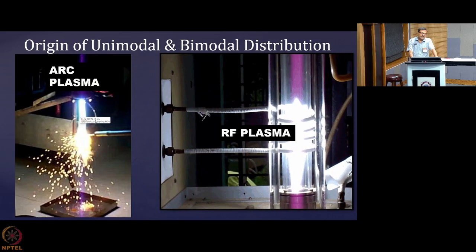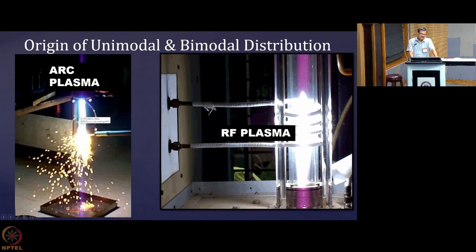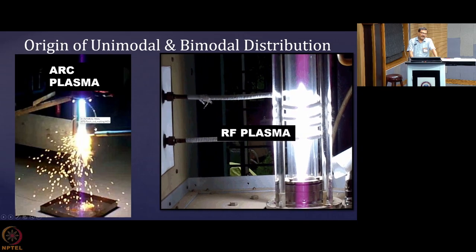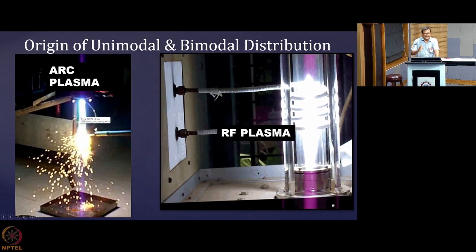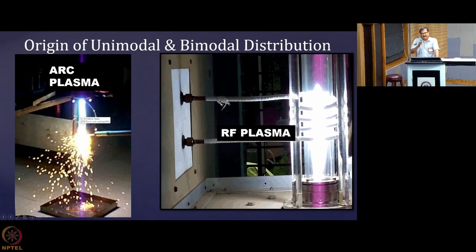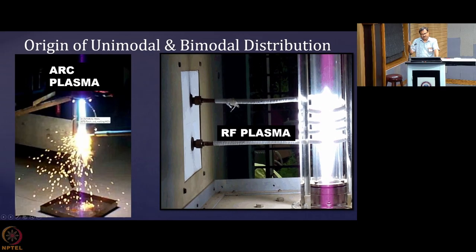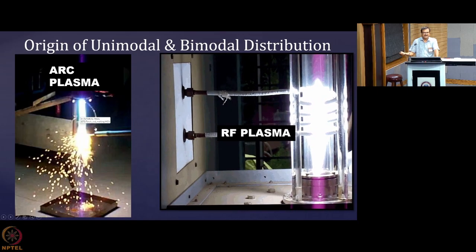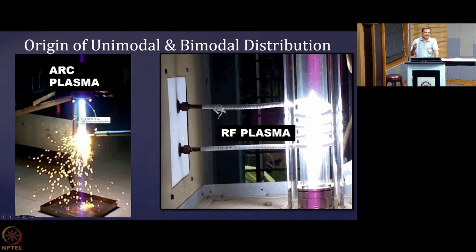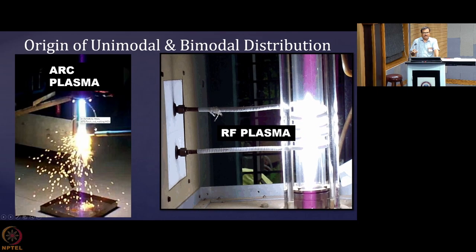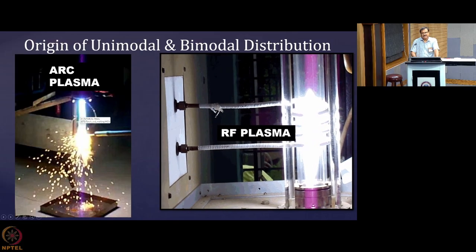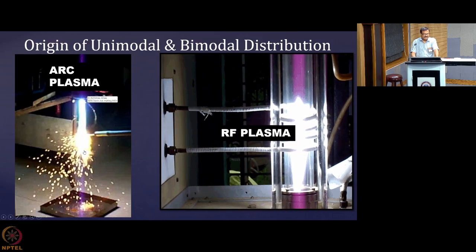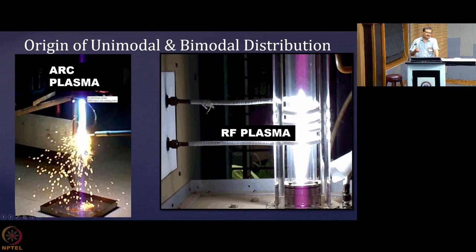The high gradient in radial direction causes the particles to have much finer size, because with the higher gradient, the nucleation is stopping much faster, so they are not able to grow enough in size and giving you particles of smaller diameter. Whereas when they are moving along the axis, they are colliding,